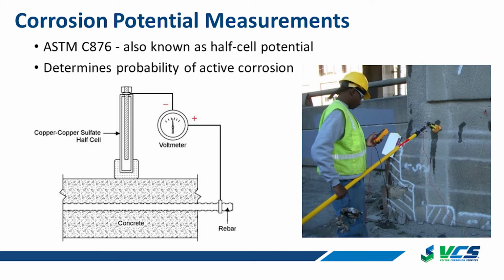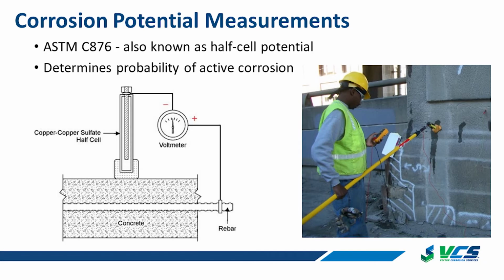So we also did some corrosion potential measurements to look at corrosion activity on the elements. Corrosion potential measurements are per ASTM C876. What we're doing there is we've got a reference electrode, and we're measuring the potential of that reference electrode against the steel reinforcement. And the potential will tell us the potential risk for corrosion activity of that steel reinforcement. And you see here this gentleman in the bottom right corner, he's got that reference electrode, and he's looking where the active corrosion is beyond where the concrete is delaminated.